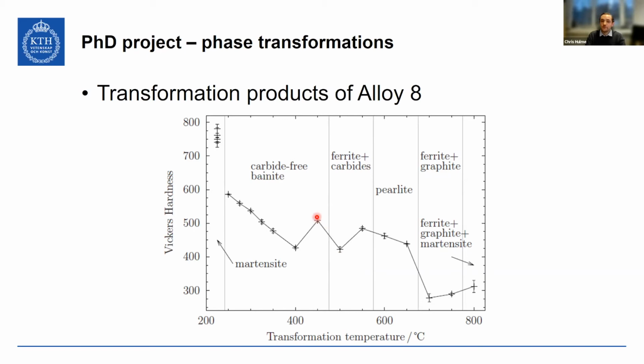And of course, at this point, it wasn't necessarily nanostructured. But as we go to lower temperatures, it did become nanostructured. So, very well behaved. And then below this 240 degree limit, the transformation product, I think this was at 225 Celsius, was martensite everywhere. It follows a very nice pattern, and it was very beautiful, sort of a textbook transformation.